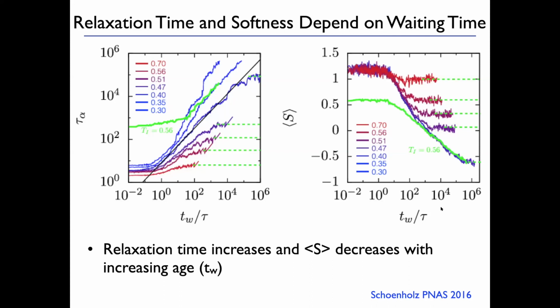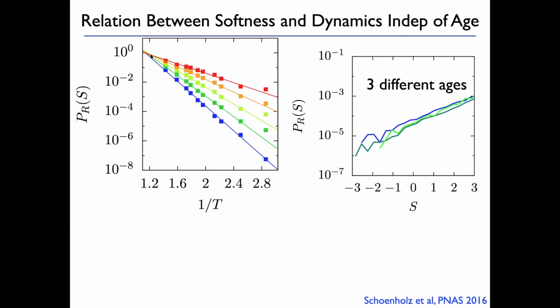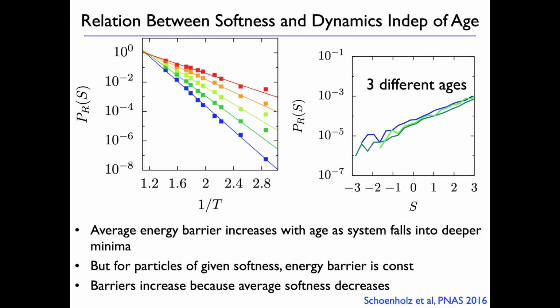Now, I can plot and look at the probability of rearranging at a given softness even as I'm out of equilibrium. And what you see is it falls exactly on the same lines that we had before. And so at different ages, the probability of rearranging as a function of softness is the same as it was before. So what that tells you is that as you age, the system is falling into deeper and deeper minima, the energy barrier is increasing, okay? But for particles of given softness, the energy barrier is the same as it was before in equilibrium. And the reason why the energy barriers increase with time is because the average softness is decreasing, okay?